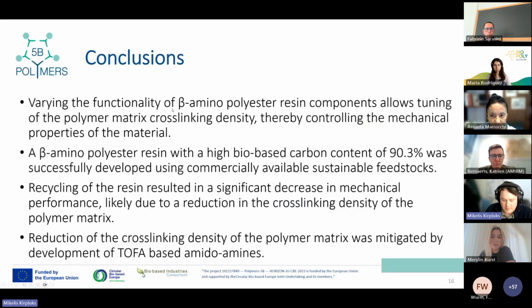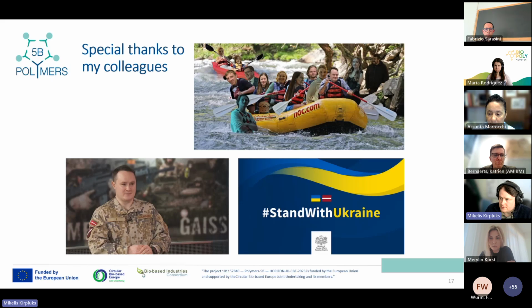it is possible to mimic polyurethane materials by using beta-aminopolyester resin chemistry to develop vitrimers that can be recycled. You just need to carefully design the matrix of the polymer that you want to use, because if you add these glycerol-based ester components, then the mechanical properties will not stay the same after the recycling cycles. At the moment, we are trying to mitigate it by developing TOFA-based amidoamines to use for the vitrimer development. Special thanks to my colleagues, and thank you for your attention.